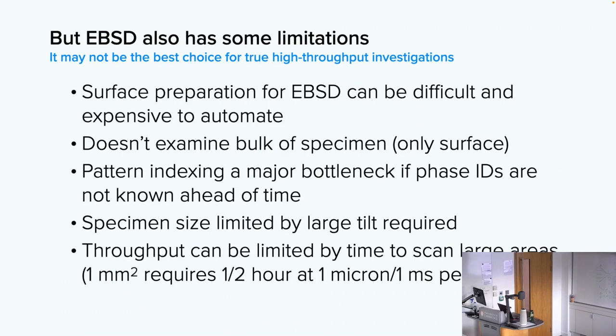And the reason is that EBSD has some important limitations. And maybe the most important limitation is in the context of a high-throughput autonomous lab, where you're potentially looking at many different kinds of materials. Preparation of the sample becomes a huge challenge. If you've done EBSD, you know that your success or failure often depends on how good a job you can do of preparing that surface. The idea that we could use something like a RoboMet to do surface preparation, yeah, we could do that. Thus, the RoboMet itself was going to be about half of our budget for structural characterization. But the real interesting part of that problem is, if I have an unknown material, how do I develop the recipe that I need in order to let the RoboMet do its job? And so that seemed like a research project in its own right.